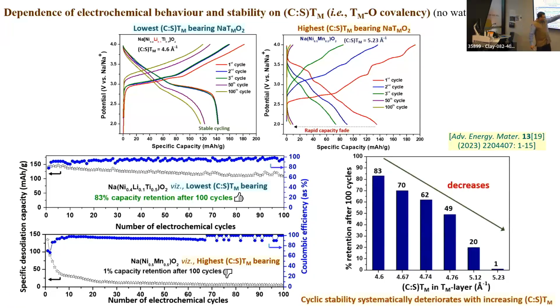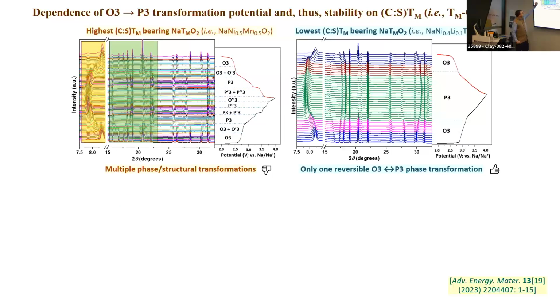Okay, so this shows that as the charge to size ratio of the transition metal layer goes down, my cyclic stability increases for all the materials. So when we did the in situ XRD, what we figured out was the one with the highest charge to size ratio underwent all possible structural transformations during charging, and no wonder the structure was totally unstable. The structure got damaged during the cycling and it showed a drastic capacity fade. By contrast, the one with the lowest charge to size ratio bearing transition metal layer showed just one O3 to P3 transformation, which is known to be reversible, during the entire charge and discharge. Whereas this one had undergone multiple transformations, all possible transformations. And the ones with intermediate charge to size ratio followed suit.